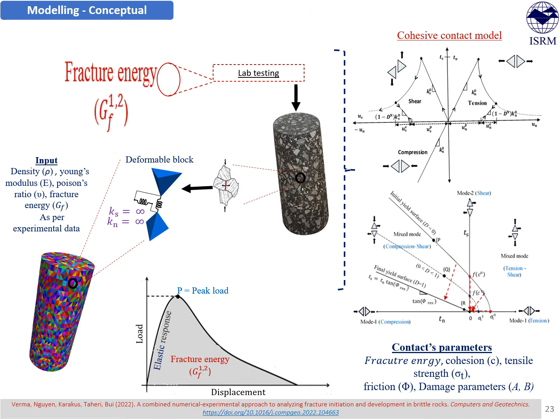Now when we subject this rock specimen to any given loading condition, for example uniaxial compression, this specimen cracks because of the loss of intergranular cementitious forces, and the crack in the majority of cases is due to the loss of these contacts, not because of grain crushing.